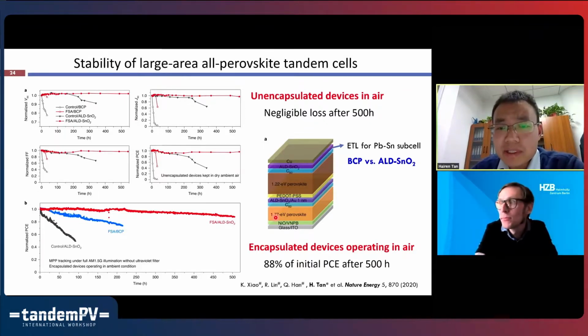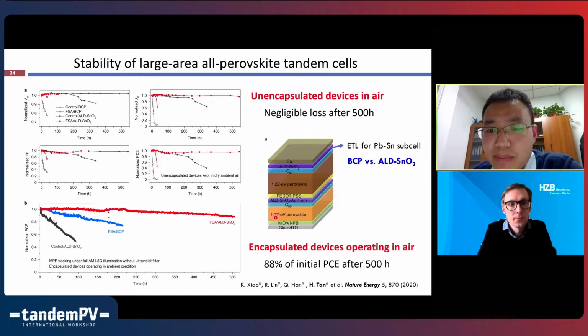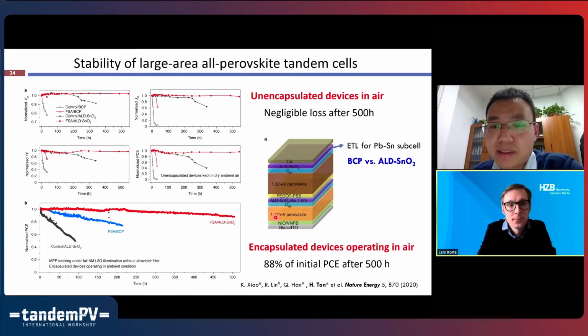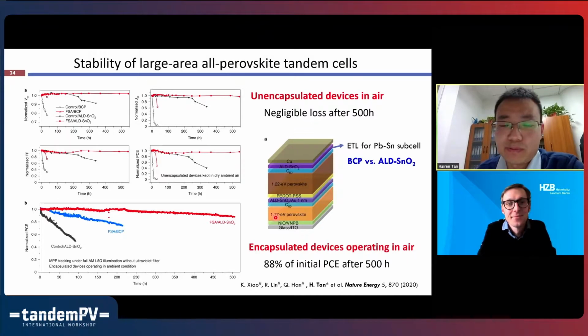We haven't studied the composition or properties of this layer in very deep detail, but we usually found that this layer, processed by atomic layer deposition, is quite reproducible, especially on top of the lead-based perovskite. Reproducibility is not a problem, at least in our lab. Almost all the lab members can make good layers on top of the lead-based perovskite films. But we do find that it's quite tricky and interesting to deposit this layer on top of the lead-tin perovskite layers. It seems that it's quite sensitive to the processing parameters.